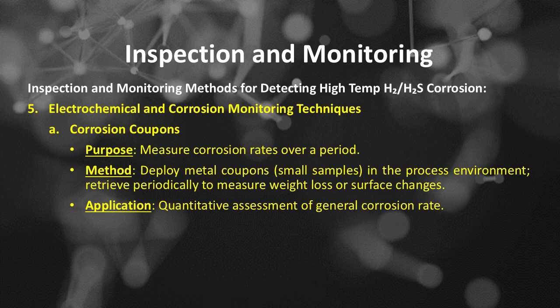Inspection and monitoring methods. Number 5 is electrochemical and corrosion monitoring techniques, which includes: Number A, using corrosion coupons. This is purposed to measure corrosion rates over a period. The method of using corrosion coupons is to deploy metal coupons, small samples, in the process environment, and retrieve them periodically to measure weight loss or surface changes. The application of using corrosion coupons is quantitative assessment of general corrosion rate.